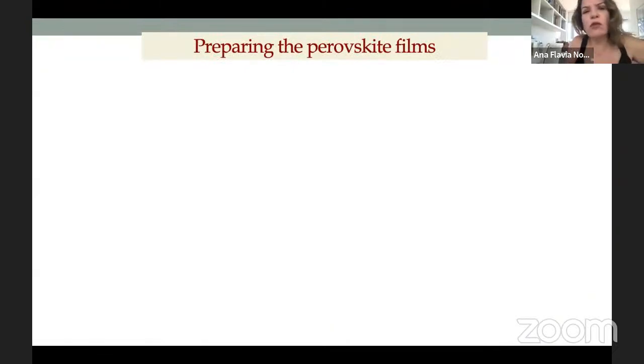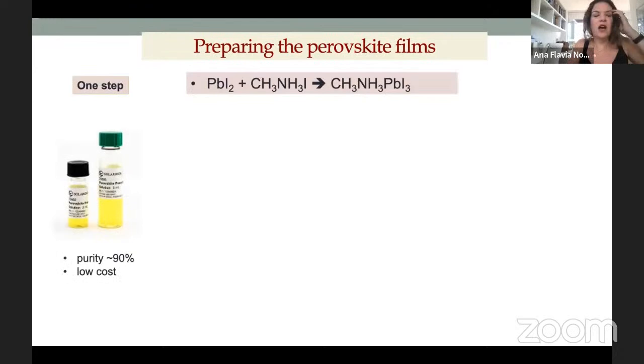Okay, well, so let's talk about the films, because films are of much more interest for PV. The one-step method is nowadays the most used method to prepare the perovskite. Basically, we start with the precursors in solution. You can just use regular precursors. The purity is around 90%, it's low cost. You just mix, for instance, lead iodide with methylammonium iodide, and then you have a solution of the MAPI in this case.